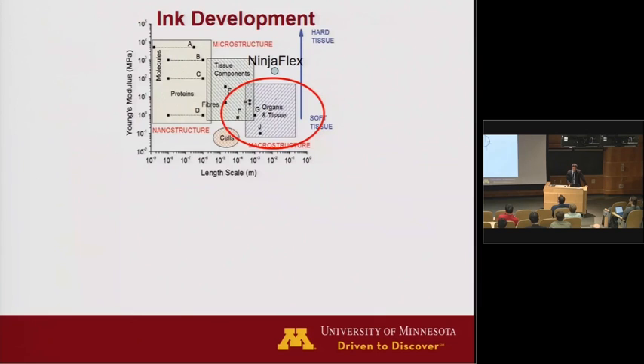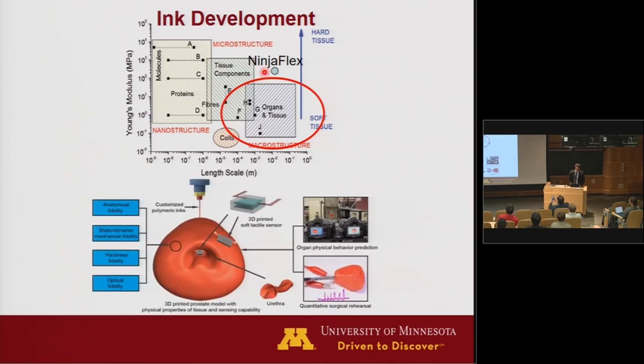That's the idea. And if you look at some of the 3D printing inks that are out there, some of the filaments, the Young's moduli of these filaments, the soft ones are typically on the order of the megapascal range. So even NinjaFlex has a shore hardness of 40, it's basically about 15.2 megapascal in terms of Young's modulus. This is well beyond orders of magnitude higher than the feel and touch of organ and tissue, the Young's modulus of actual tissue samples.